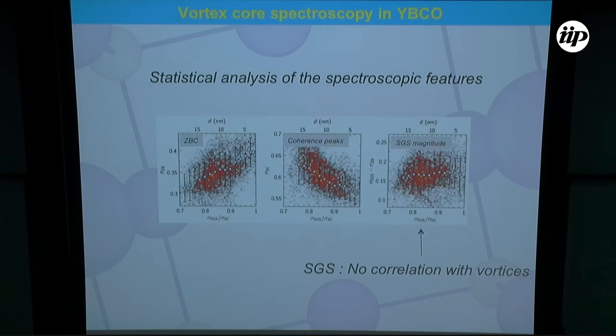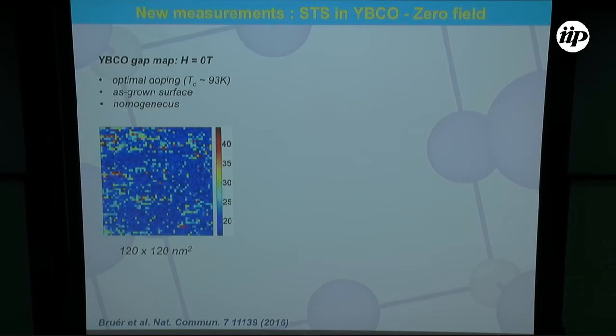By performing a statistical analysis of the spectroscopic features, you can see that the X scale of these diagrams provides the position compared to the center of the core, 1 being the center and the smaller number being the outside of the core. When you enter the core, the zero bias conductance increases, the coherence peaks decrease, but the subgap state magnitude remains constant. So there is no correlation between the subgap states and the vortices.